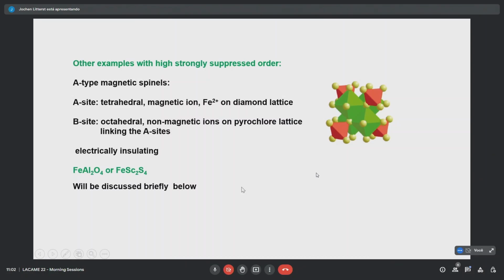There are other examples where we find highly suppressed magnetic order. If you go down below the Curie-Weiss temperature, you cannot see that the spins will really end up in magnetic order. A typical case for that is the so-called A-type magnetic spinels. Spinels, you know, have a cubic structure, and the substructures are like this. That's the A site, that's tetrahedral, and that's occupied in this case by divalent iron, sitting on a diamond lattice. And those are the red